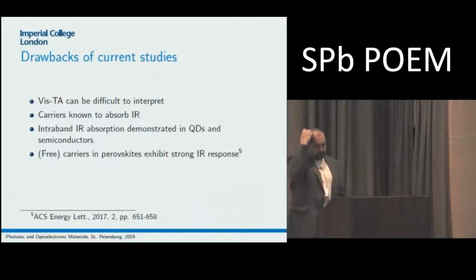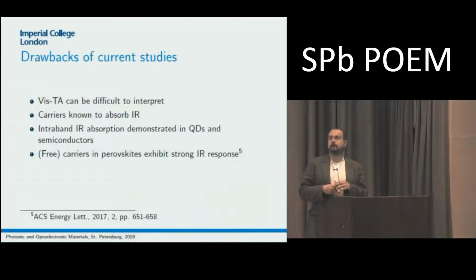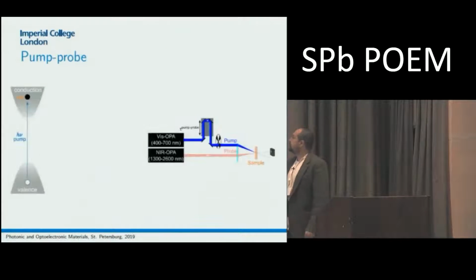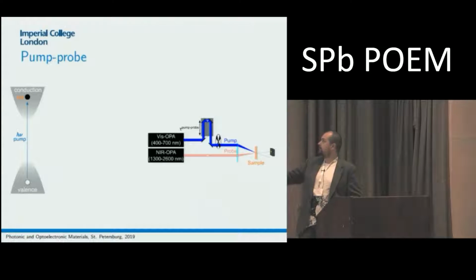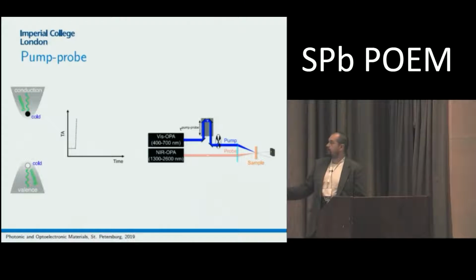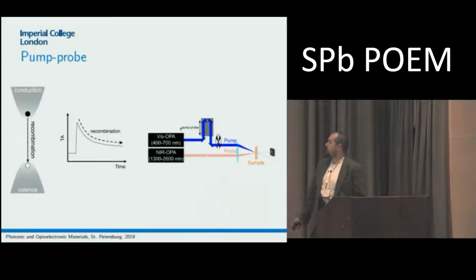Most studies are being performed by just normal transient absorption, when the sample is pumped with different wavelengths, and people measure the pump probe characteristic times and try to see the difference between carriers pumped at different wavelengths, and thus derive the effect of hot carriers versus cold carriers. This is a normal pump probe setup, where usually a visible beam is used as a pump source, and some near infrared probe is probing it and is being measured. What is happening is that we have the change of transmission, and then we just look at recombination versus time and we can derive the dynamics of carriers there.